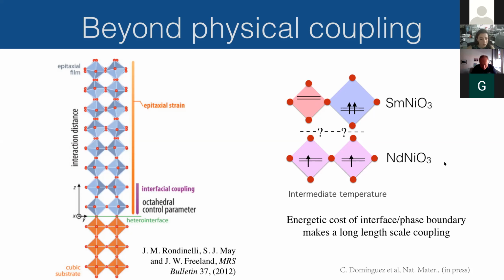So I just wanted to show this example to say that we found something that goes beyond interfacial coupling. It cannot be explained by epitaxial strain because the whole structure is strained. And what we've shown is that there is in fact something else. There's something that is not a physical structural coupling at interfaces that is dominating, and it is determining the physics. So this is something that we're definitely going to pursue in the future. The paper will be out soon, so look out for that.